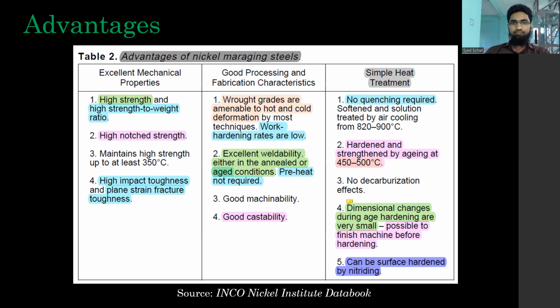Good machinability. This is something we utilized a lot, as we'll see in the machining slide. From the heat treatment perspective, it has a simple heat treatment in the sense that no quenching is involved. Firstly, the heat treatment is very simple. As we'll see in the coming slide, you have a certain temperature and a certain time, which is very nominal: 3 to 5 hours for aging and 1 to 2 hours for solution treatment. So that is what gives this simple heat treatment benefit for this material.